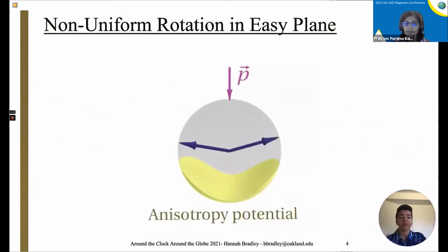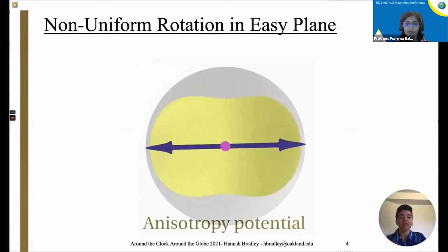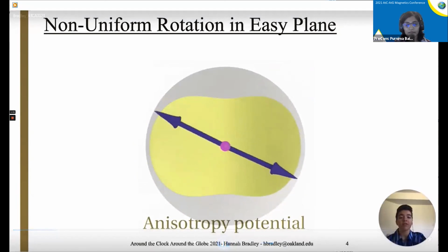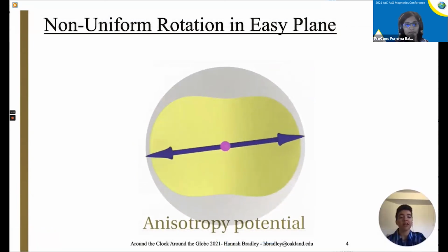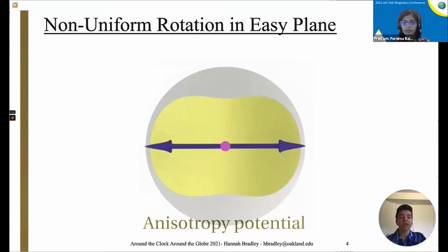The spin current acts on both magnetic sublattices and causes them to rotate, but the anisotropy of the AFMs causes this rotation to not be uniform. The rotating spins create a spin pumping signal, the magnitude of which is proportional to the rotational speed. The non-uniform rotation at a terahertz frequency results in a sequence of very intense, very short spin pumping spikes.